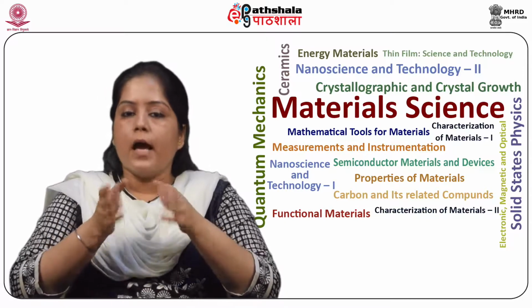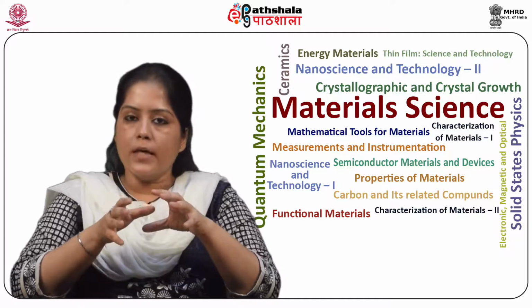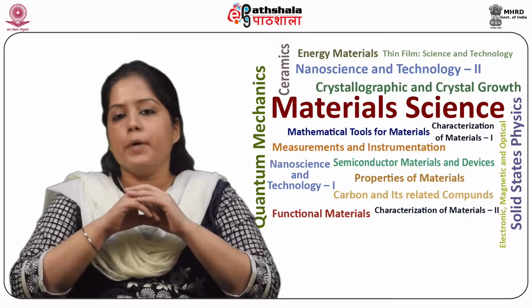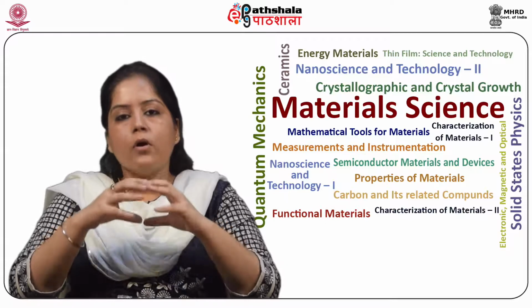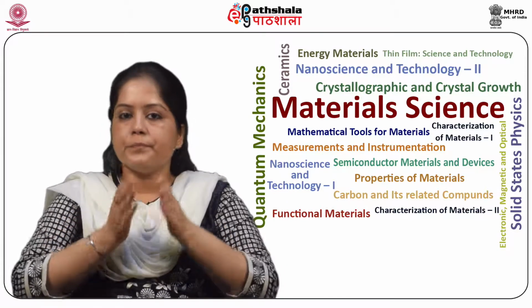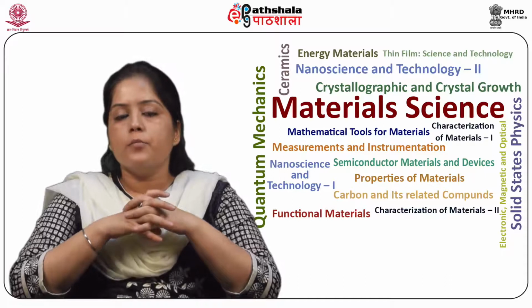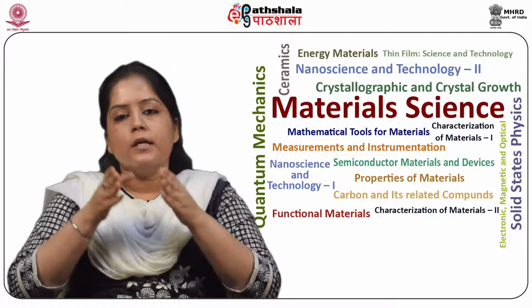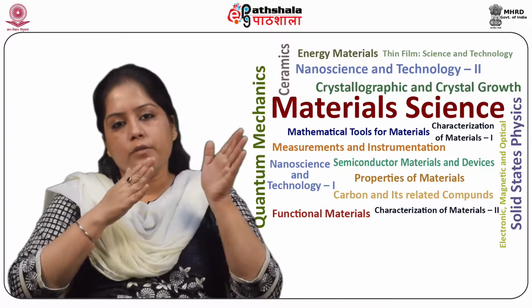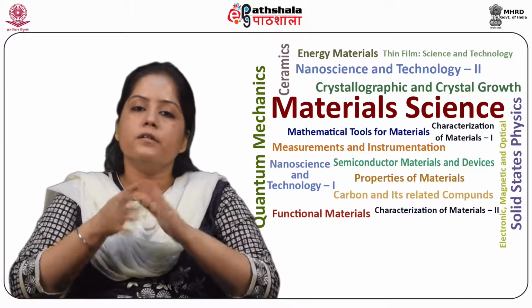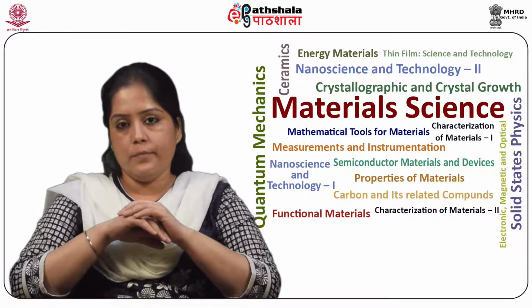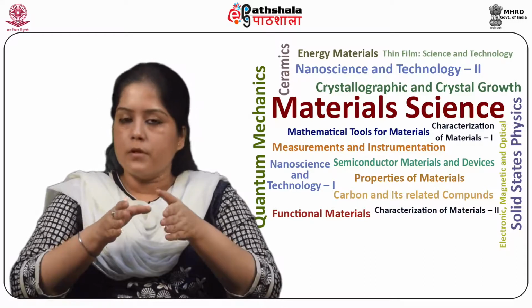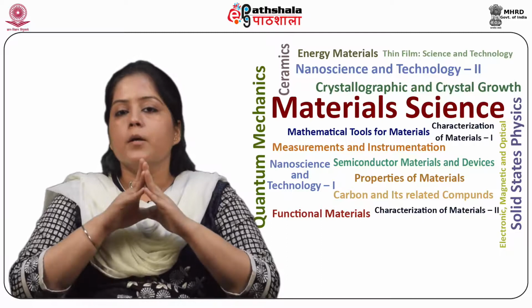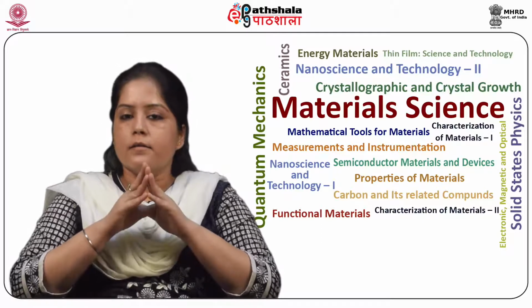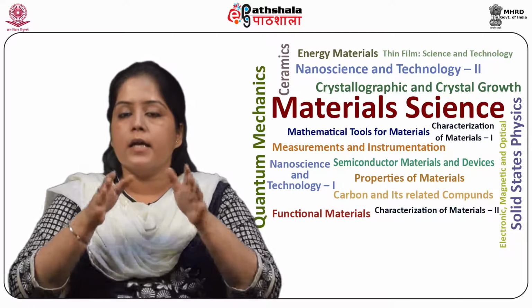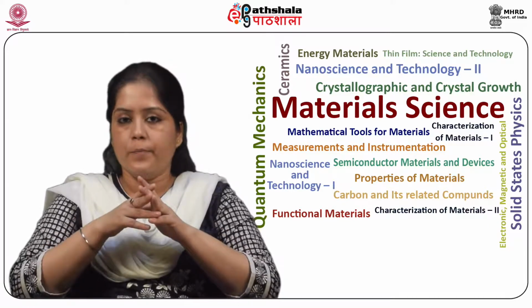So when an electric field was applied to the ordered perovskites, the smaller rattling space for B-site ions prevented the motion, resulting in the development of strain and further distorting the octahedron. Thus, it was observed that the ordered B-site cations resulted in enhanced electrostriction property.